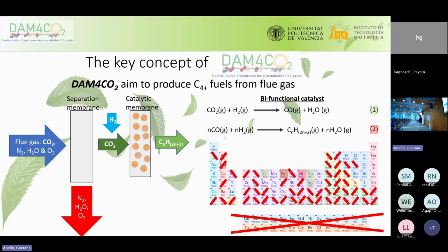These two catalysts perform the CO2 hydrogenation very well, but they perform this reaction so well that they normally stop at methane. So to push the reaction to longer alkanes, you need to choose other metals, other elements, that push the reaction this way. So one of these are the enhancers. We call them enhancers; as an example, we are using manganese and zinc.